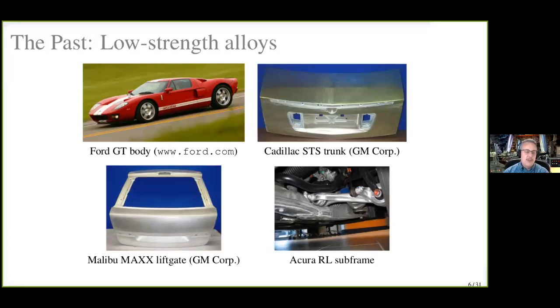Low strength alloys have made a lot of penetration into the automotive market. And these are examples of high temperature formed materials. We can get huge ductilities in the aluminum at high temperatures, and particularly the 5000 series alloys. So here, the Ford GT, the outer body panels were formed by Superform USA, a specialty forming outfit, and they were bought by Ford. And that's a 5083 alloy, not heat treatable, fairly low strength. 150 to 200 MPa is about all we have there.